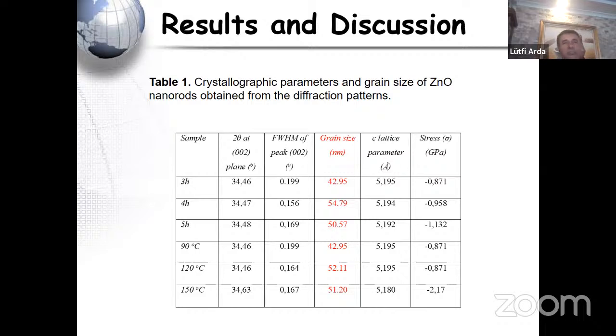I thought in the material part, we use a seed layer, and this zinc oxide seed layer is coated on the substrate before the hydrothermal growth to prevent the lattice mismatch between the substrate and the nanorods, which creates various structural defects on the film surface. Despite this, unhindered thermal and elastic mismatch strain could be responsible for the residual compressive stress in the crystal structure of zinc oxide.